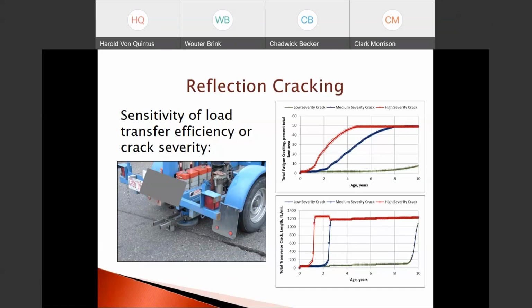The graph on the right shows the total fatigue cracks, bottom-up fatigue cracking. The red cross-hatched line represents high severity. The open blue circles represent medium fatigue crack severity, and the green plus line on the bottom shows the low severity bottom-up fatigue cracks. And as you can see, the crack severity and load transfer efficiency is extremely important.